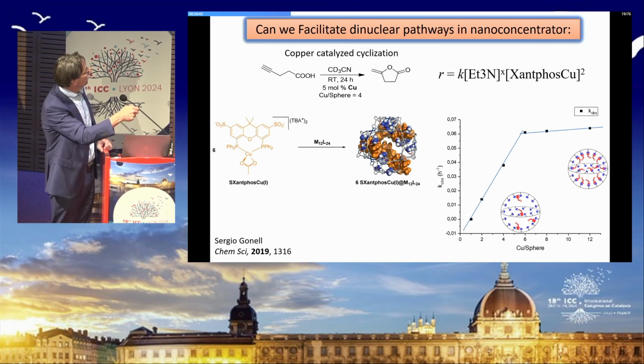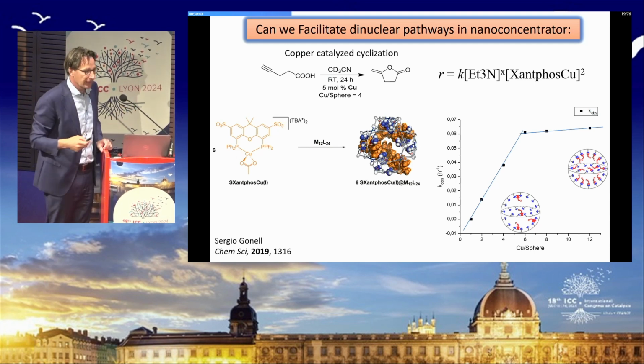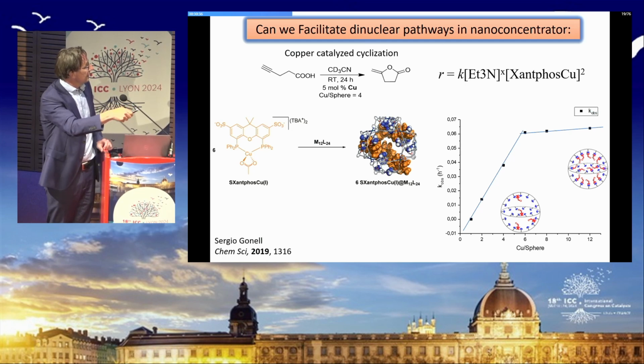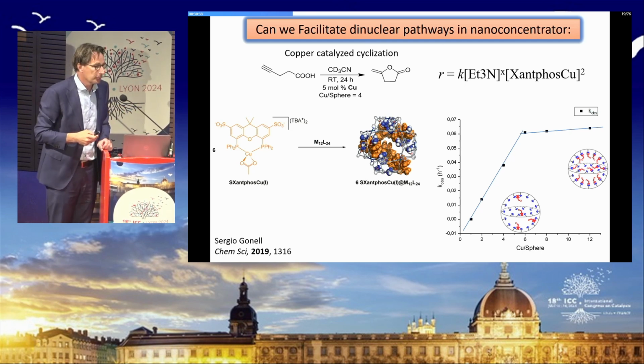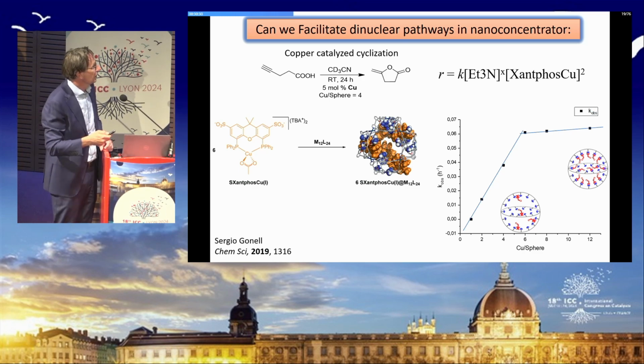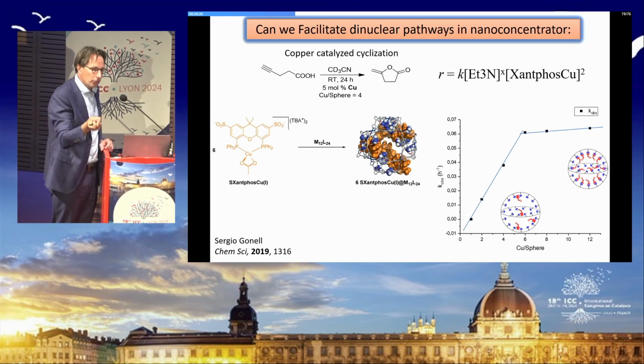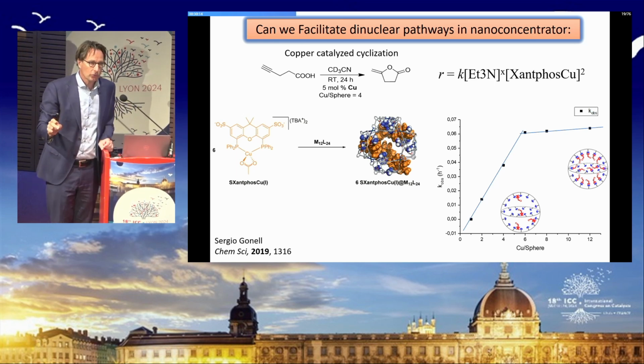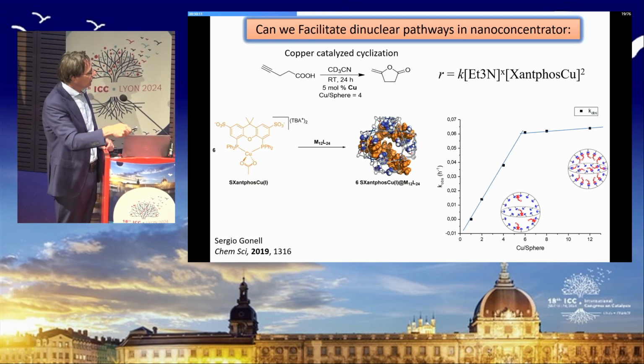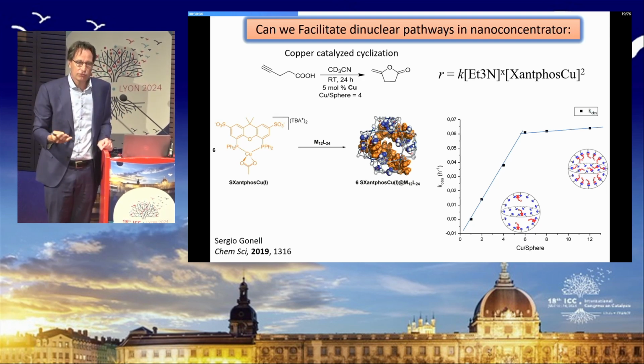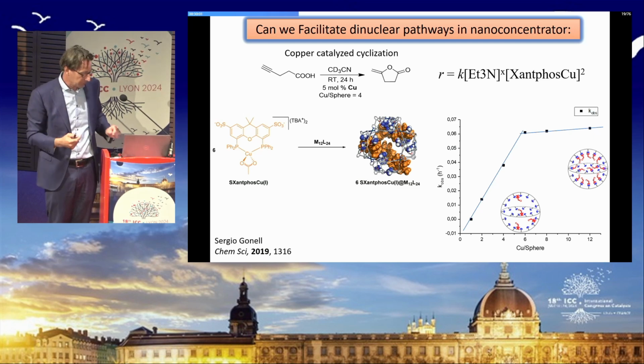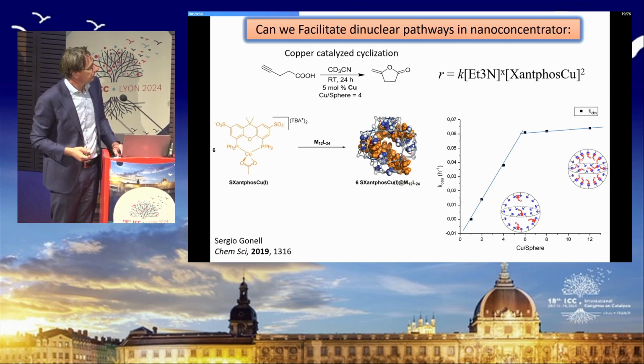And this is exactly what we observed. So we redesigned the catalyst by adding sulfonate groups so it can be bound. So this is 6 complexes bound in the cage, and we can bind up to 12 according to our NMR experiments. And then we tested that in this cyclization reaction, and here we have a graph where we change the copper sphere ratio, so the amount of copper catalyst effectively loaded in the cage versus the rate. The overall copper concentration is the same in all experiments, and you can see that by just pre-concentration, you can increase the reaction rate by an order of magnitude on the basis of a rationale based on the mechanism.